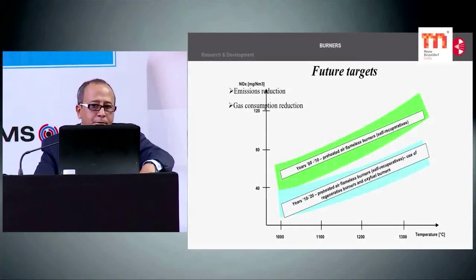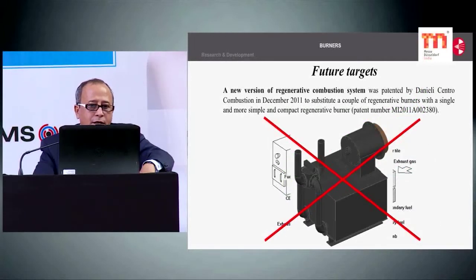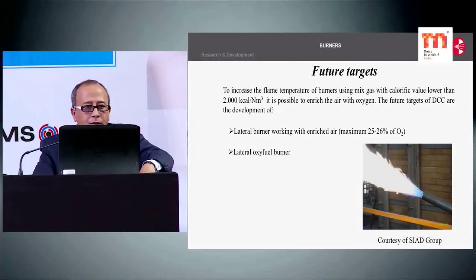This is again a patented burner of Danieli. So it's a high-speed recuperative, self-recuperative burner, wherein we can preheat the air to the burner to around 800 degrees centigrade if the furnace temperature is up to 1000.